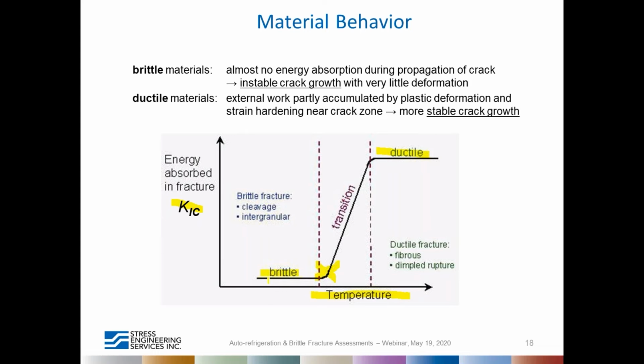Brittle materials exhibit almost no energy absorption during the propagation of a crack, but in ductile materials, when external work is applied, it gets partly accumulated by plastic deformation or strain hardening. So there is more stable crack growth in those cases. Every time a material gets cold, especially carbon steels, it is of concern because of this behavior.